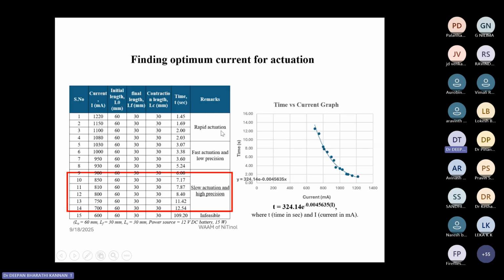Depending upon the application, in some cases we may need rapid actuation. In some cases we may require slow actuation. What they found from their initial preliminary data, as shown in the slide, is that when the current is on the higher side, that is 1220 milliamps, the actuation was very rapid. You can see that within 1.45 seconds, they were able to return to the original shape. But with lesser current, around 850 to 700 milliamps, the actuation was slightly slower, taking around 12.54 seconds. When they were supplying a current of 600 milliamperes, the temperature was not rising to the austenite finish temperature. As a result, the shape change was not happening.